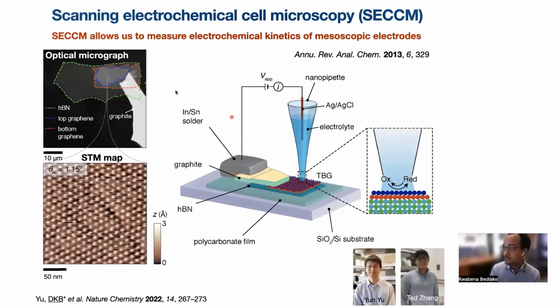So here is an optical micrograph of the device where we have a twisted bilayer graphene sitting atop hexagonal boron nitride, and then we have a contact here. We get STM, these are just ambient STMs, also using the NX10 system. And so we can visualize the Moiré superlattice by mapping using STM, and that confirms it. But then we go ahead and do our scanning electrochemical cell microscopy measurements. And I'll just walk you through one example.